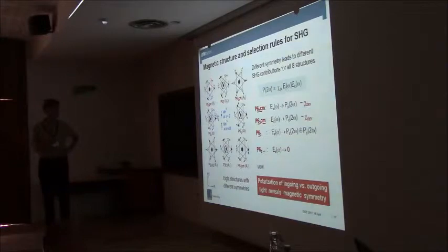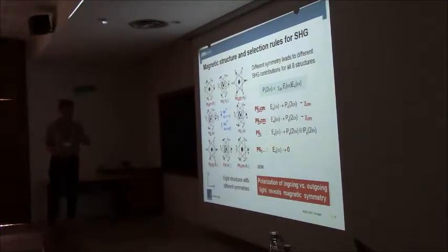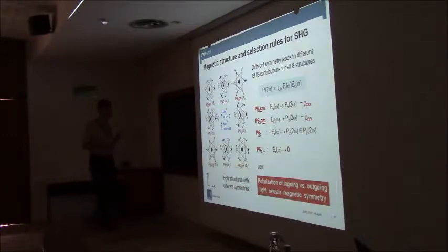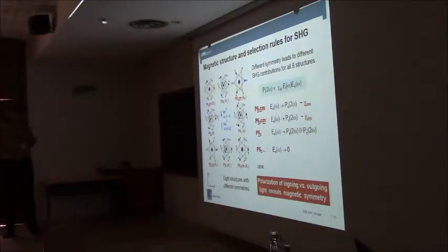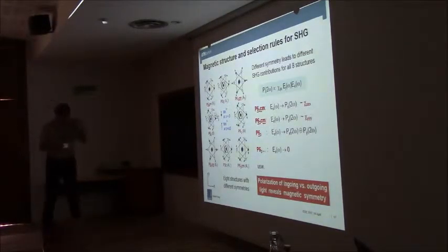The funny thing is, if you have these three structures, and those 3, neutron diffraction, which you would typically take for analyzing the structure, cannot distinguish between these and those. So these compounds were discovered in the 60s, and until 2000 it was not really clear if they're ordered like this or like that. And that's really a bit surprising, imagining that they are so already around for such a long time.